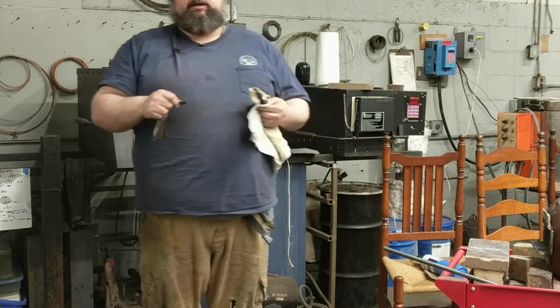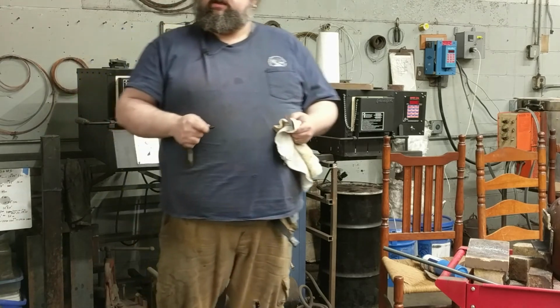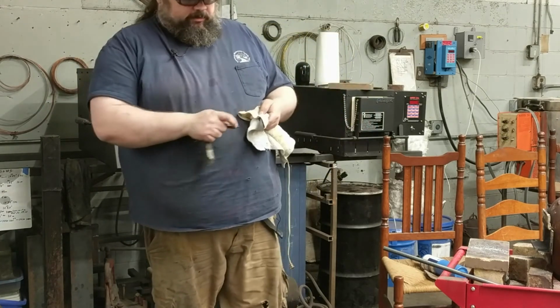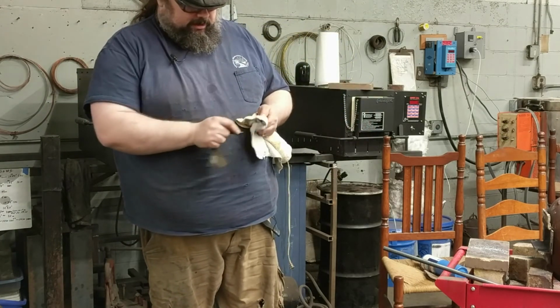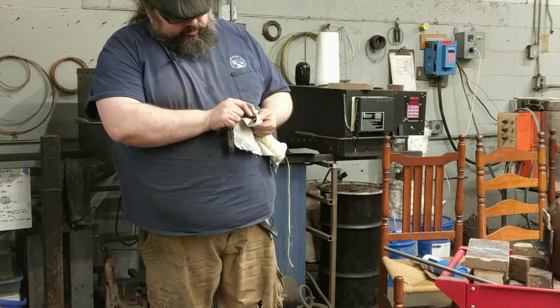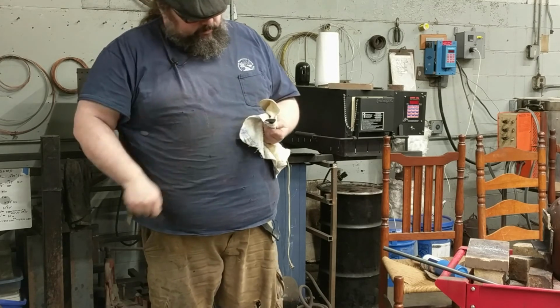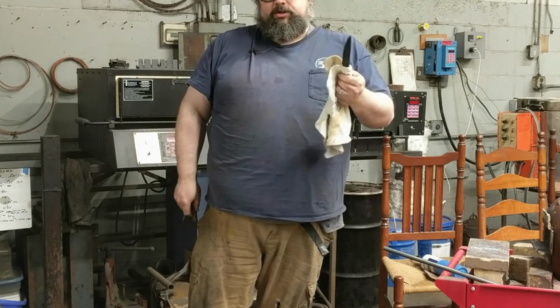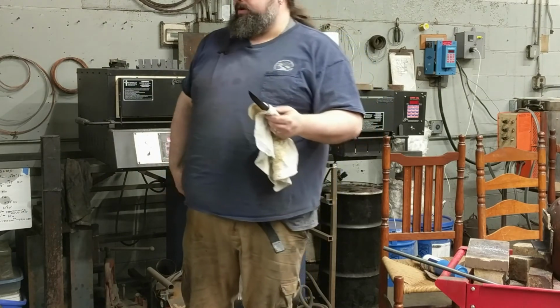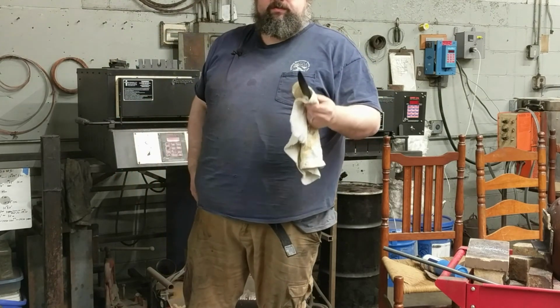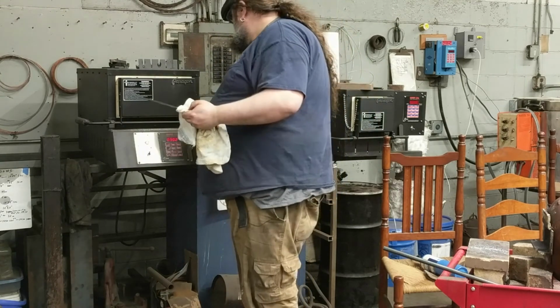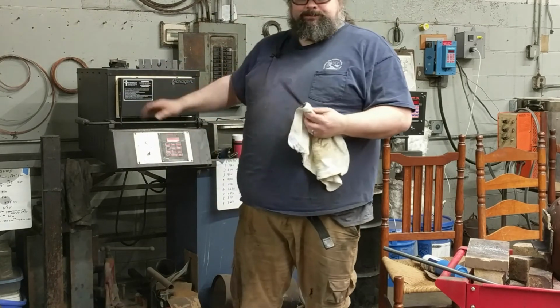If you have a lot of decarb or scale on it from forging, you want to grind that off before you check to make sure it's hardened. That's hardened. Looks like my bolster even hardened also. Beautiful. Now that I'm sure this is hardened, I'm above 64, so I know I'm at least pretty close to optimally hardened. Then I'm going to put it in the oven.